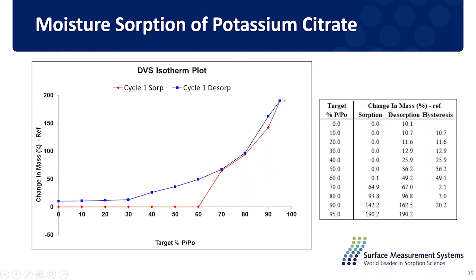And the total uptake could be more than 200%, which is basically just the condensation of the water on top of the material. And during the desorption branch, it didn't go back to zero. So it's kind of an irreversible phase change. Maybe some water is still trapped in the material after the desorption branch. So we have the equilibrium moisture content on the right-hand side from the report.